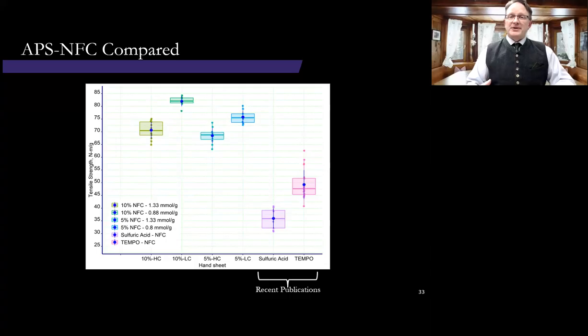Finally, I want to bring us back to a comparison of the other two chemistries, sulfuric acid and TEMPO, specifically with regard to tensile development. So these blocks here represent the tensile development in our samples relative to recently published sulfuric acid and TEMPO. And I selected papers that use the same retention chemistry that we did. And what you can see is that ammonium persulfate, both surface charges, developed a much stronger sheet and matched the reduction in permeability compared to recently published research for sulfuric acid and TEMPO reinforced papers.